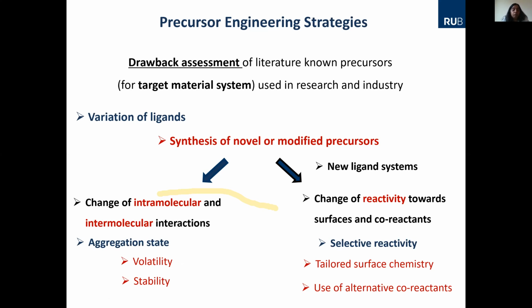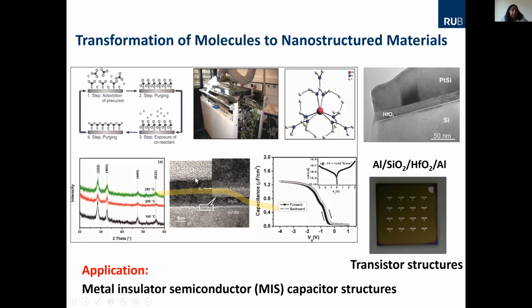So in that case, what we do is, so this is a schematic where I can show you. This is the ALD principle, what I mentioned before, where we have the pulse and purge. Then you have a reactor where you introduce this molecule here in this channel. So this is a precursor molecule. You see, you have metal and a ligand surrounding it. And this molecule is then transformed to form a material. So here is a TEM picture of a silicon substrate, and the hafnium precursor, what is here, it's reacted with water and it forms the hafnium oxide layer here.